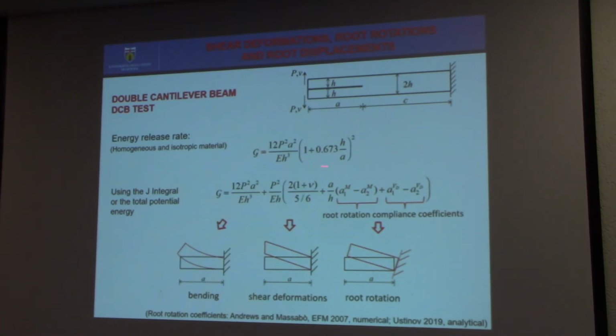And you can see that here in brackets we have this term which is squared. Now, if we apply the J integral and we introduce shear deformation, root rotation, and root displacement coefficients in our solution, we can explain this term and separate all the different contributions. So the first important contribution is bending of the delaminated arms, and this is the dominant contribution. It goes with the crack length squared.